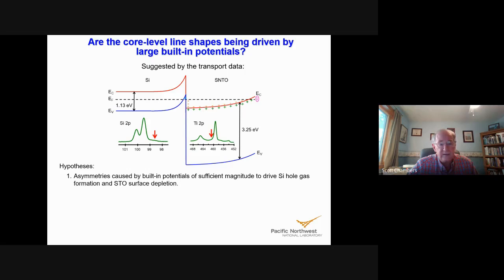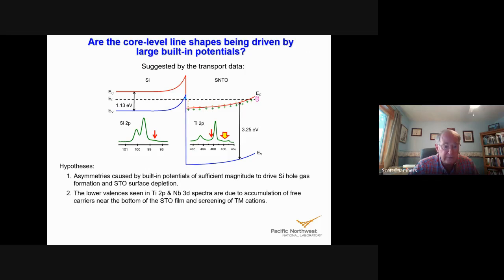Because I didn't show you this in the transport data, but there is indication that the band bending at the surface of the STO is high enough that you actually have a depleted region right at the surface. So that was one hypothesis. The second hypothesis is that the lower valences that are there in the titanium and niobium spectra are due to the accumulation of free carriers at the bottom of the STO film, which screen the transition metal cations that have their nominal charge for that lattice.